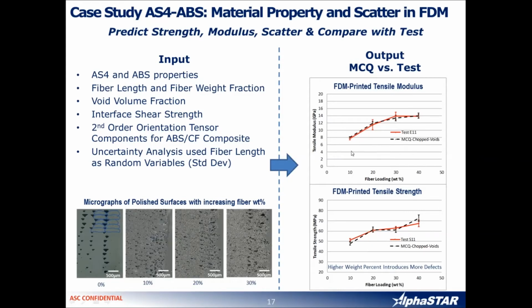And you can see that for the modulus, as the weight fraction of the fiber increases, it almost becomes like a plateau here. It saturates. A similar thing is also observed for the tensile strength as well. It increases, and all of a sudden there is a decrease in the slope here. So that clearly shows that increasing the weight fraction of the fiber does not really help to increase the modulus or the strength. It can also sometimes decrease it. So there is a saturation point, and that's been clearly modeled using MCQ Chopped software and has been validated with test.